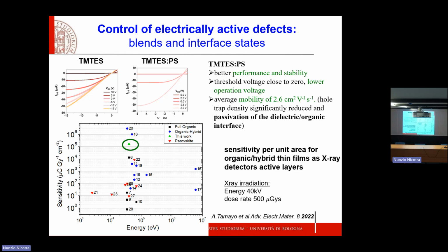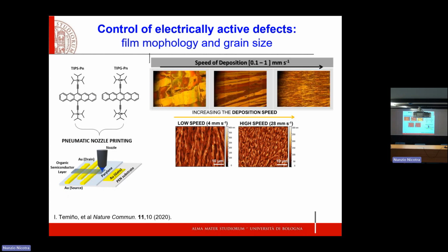And it is much higher because you're passivating the traps that are negatively affecting the transport for majority carriers. And that is why we get a much higher sensitivity, so a much higher gain for ionizing radiation X-ray detectors, okay? So we can learn how to passivate majority carrier traps that are killing the mobility in our material and leaving the mobility high. The other traps that we have to control are the traps around our crystals, our polycrystals. Why? Because that's where the electron trapping happens, so the minority carriers get trapped. And these are the traps that are more directly related to the gain. And as we'll see in a moment, these traps are beneficial and we actually want to keep them.